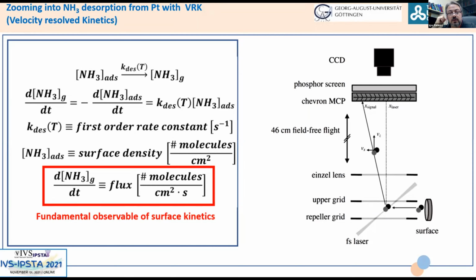So what we usually detect in most experiments is density, and this can actually lead to significant deviations. The method we are using here is the so-called VRK, velocity resolved kinetics. Briefly, the ammonia molecules produced in the molecular beam land on the surface, then they desorb, and then we detect them using multiphoton non-resonant ionization, which is a universal means of detection. Then a pulse of electric field is applied, and these ions fly in the field-free region in this time of flight mass spectrometer. And they also preserve their velocity component in the direction perpendicular to the surface.